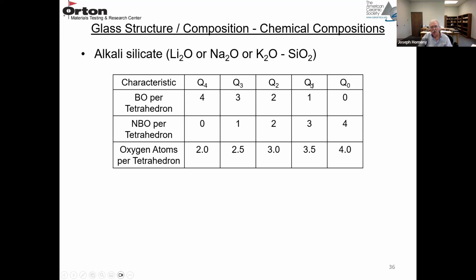So here is Q0, Q1, Q2, Q3, and Q4. And then the bridging oxygens per tetrahedron are given by this number. So if it's Q sub 4, there's 4 bridging oxygens. So that would be a pure SiO2 type glass. If it's 0, there's no bridging oxygens. And then you can have these other cases, Q3, Q2, and Q1 with 3, 2, and 1 bridging oxygens. So the bridging oxygens and the non-bridging oxygens have to add up to 4. So for Q sub 4, you have 4 bridging oxygens. You're going to have no non-bridging oxygens. And for Q0, you're going to have no bridging oxygens, but you're going to have 4 non-bridging oxygens.